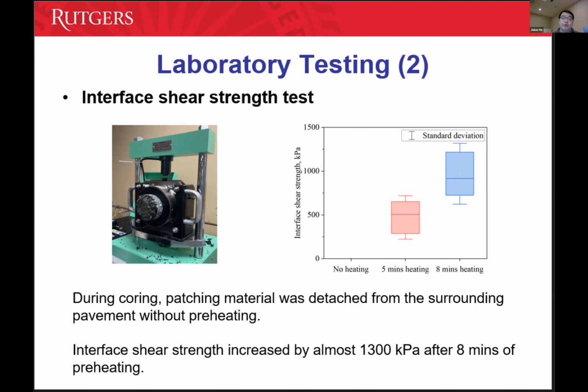So you can see basically without heating, we even cannot take the cores without any damage. When the cores are taken out, the bottom surface is just debonded. There's no bonding shear strength at all. And with 5 minutes and 8 minutes heating, you can see how the bonding strength increases. That's expected because by preheating, you are facilitating the bonding and also the flow of the binder during the patching and the quick compaction. So in that case, you have much higher bonding.